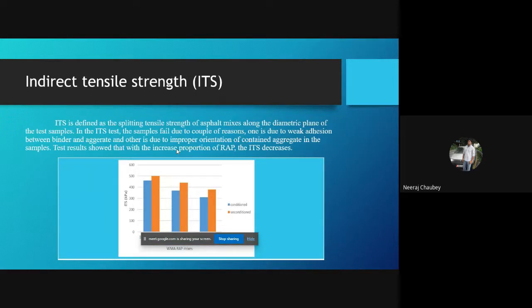This value is obtained for the indirect tensile strength. The blue portion shows the ITS for conditioned samples, and the orange is for unconditioned samples. Here we can see the ITS also reduces as we increase the RAP content.